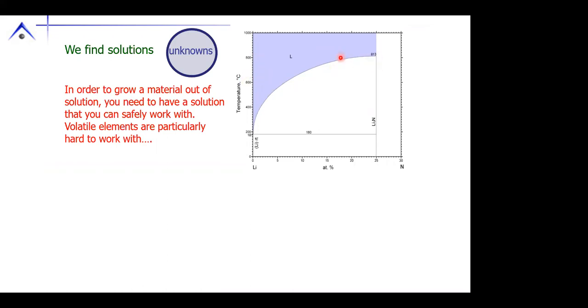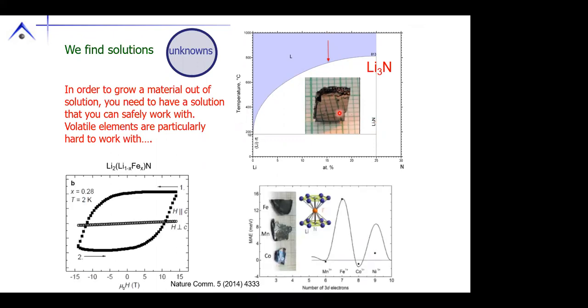Okay, now sometimes these are computationally generated and not accurate. We very carefully approached this phase diagram, and we indeed confirmed it, that if you take Li3N, polycrystalline, melt it in some lithium, heat it up, slowly cool it, you get beautiful single crystals, and you have a liquid that is actually holding atomic nitrogen in it, because this structure is not made out of N2 ligands that are well separated. So what this meant then was we could start playing around.